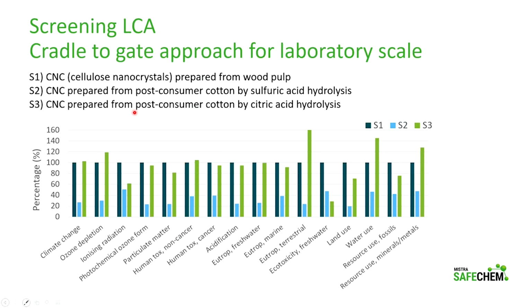I would like to take one example here where we did a screening life cycle analysis, which is a cradle to gate approach for a laboratory scale process we have developed. This is on cellulose nanocrystals prepared from textiles, but here we compared that with cellulose nanocrystals prepared from wood pulp. We used a sulfuric acid hydrolysis process as a standard method, and also a citric acid hydrolysis process, which is a newer method developed under Mistra SafeChem. So here from the screening LCA, which was done in collaboration with RISE, Anna Karin and team.